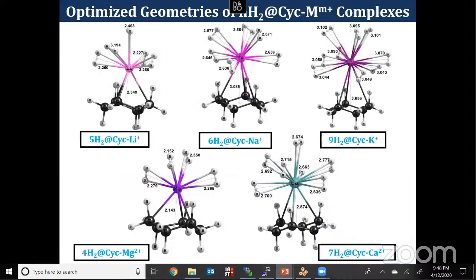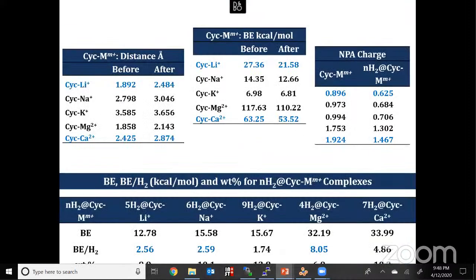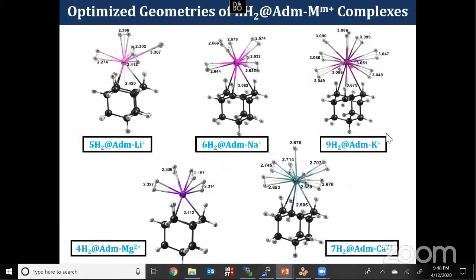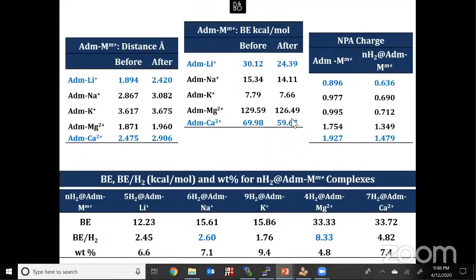Similarly, we did the same with cyclohexane and calculated the binding energy. Here also we found that the magnesium-decorated complex shows higher binding energy. There is a charge transfer taking place between the metal atom and the hydrogen molecule. And this one is for adamantane. Here also we got a similar kind of result. Among the three substrates, the magnesium-doped complex shows higher binding energy than the other four metal cations.